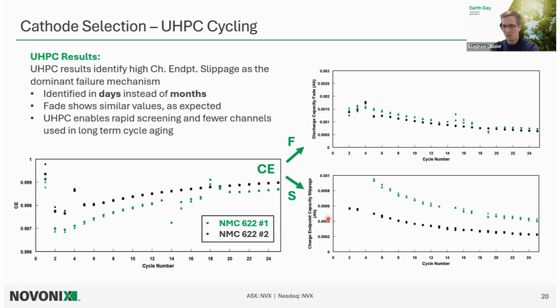But this slippage-based term is twice as big in the 622 number 1, and that's the cell that rolled over at about 2,000 cycles. So these slippage-based mechanisms going on in the background that aren't contributing to capacity fade at all are actually what ends up killing this cell over a very long period of time. So this could be something like transition metal dissolution. This could be